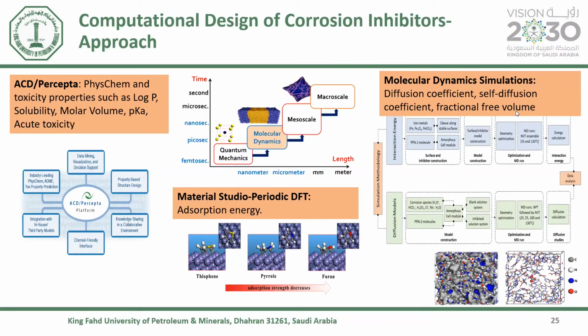We could also use molecular dynamics simulation. This is very important because corrosion takes place in the presence of an aqueous environment. And in the oil field, we have a lot of brine, chloride, and sometimes even organic acids. And then we have a lot of ions like carbonic acid, chloride, and so on and so forth. So we could use molecular dynamics simulation, as you see here, to really look at the diffusion of molecules or ions across the corrosion inhibitor membrane.